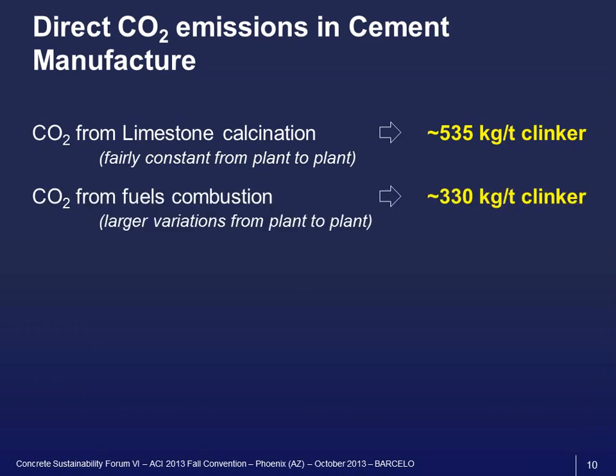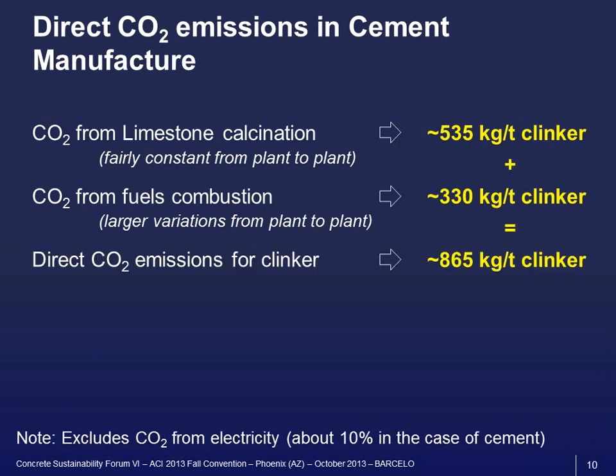The second one is the CO2 from fuel combustion, and it's about 330 kilograms of CO2 per ton of clinker. So you see it's a 60-40 split between the decarbonation and the fuels. But this number you can see larger variation from plant to plant, depending on the process that the plants are using. You add these two, and you have the direct CO2 emissions for clinker. So it's about 865 kilograms of CO2 per ton of clinker.